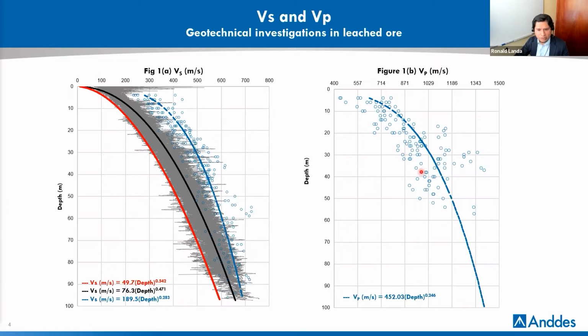And it's an interesting aspect in heap leaching as well. If the VP equal to 1500 meters per second is taken as a standard, if we take that value from the tailings, it's really important for a definition of a steady state flow regime forming a defined water table. So this is not the case in a heap leach pad, which is designed ideally to percolate the solution, of course, there are some issues with low permeability layers. And the fact that the VP is less than 1500 meters per second confirms that the regime is a transient state one, characterized by isolated pressure heads, induced, of course, by these low permeability ore layers. That is the fines dominated layers that are randomly and heterogeneously distributed, which makes assessment very difficult.